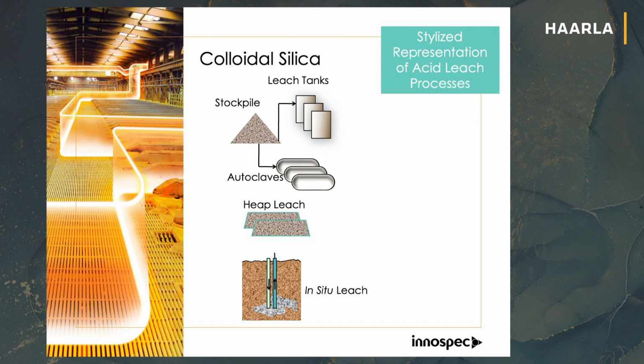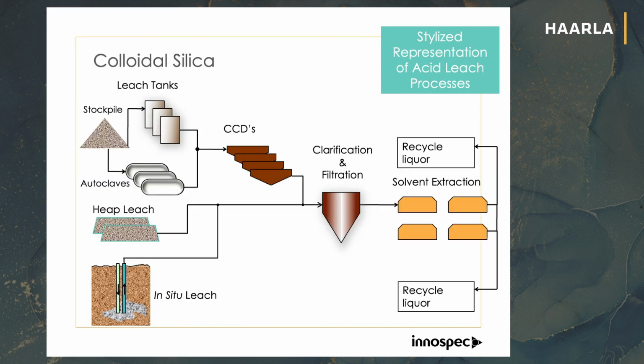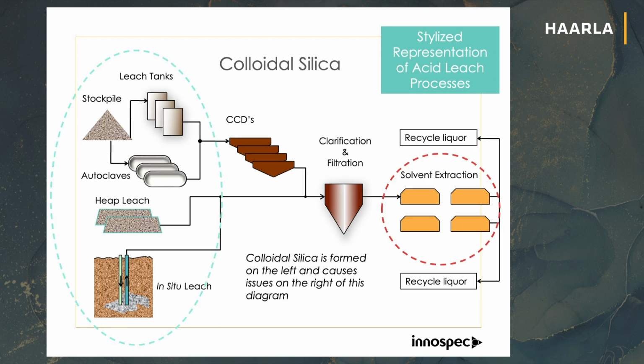I didn't talk about in situ leaching, but in situ leaching is becoming more and more relevant when you're looking at things like lithium metals. So with all of these, when you've got a high silica content, it's getting dissolved in there. You then go through your purification process, through the center part of the process, which is here, and you're trying to precipitate this, filter it and clarify it. If you're not successful in doing that, then it passes through and you have the silica problem coming through into your solvent extraction process. And that's the last thing that you want, because if it's not treated, you're going to influence the performance.